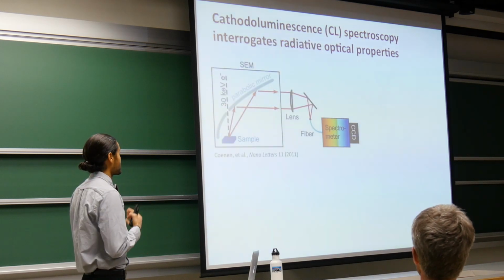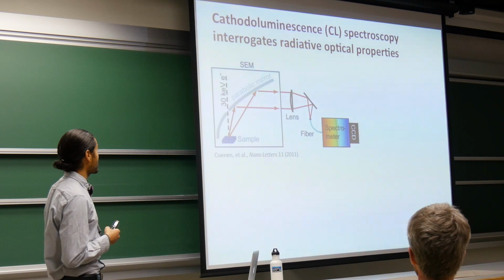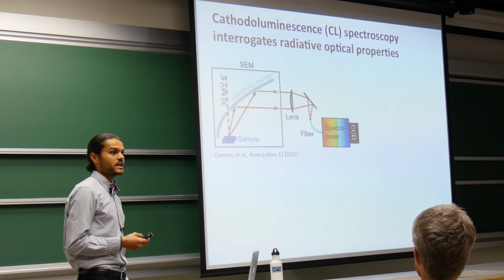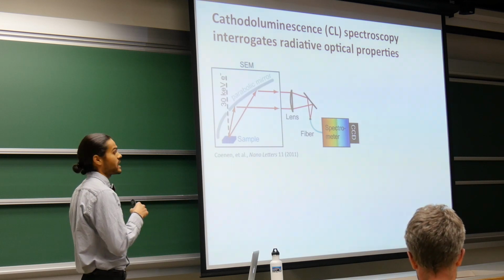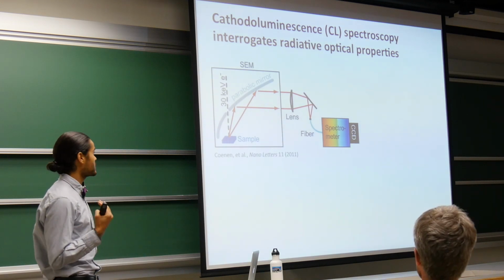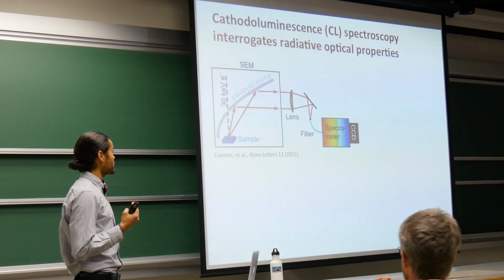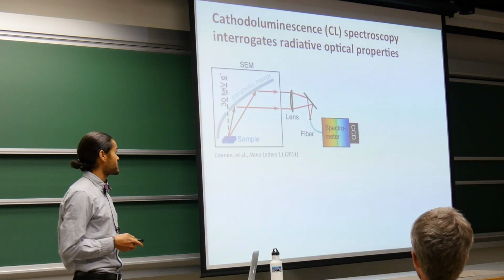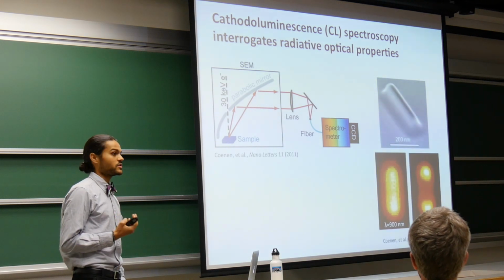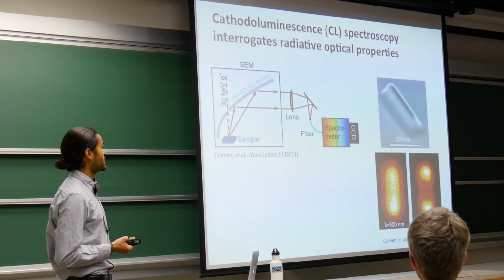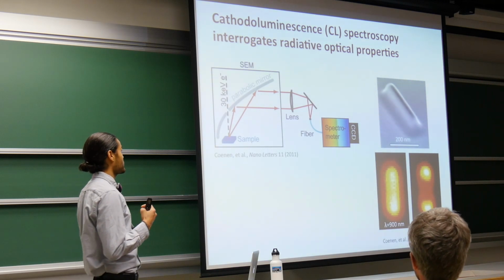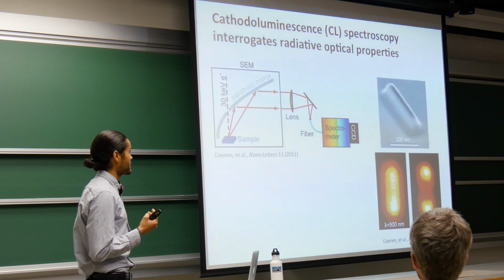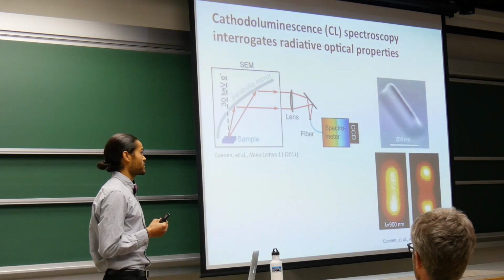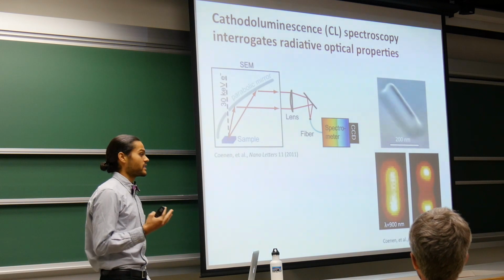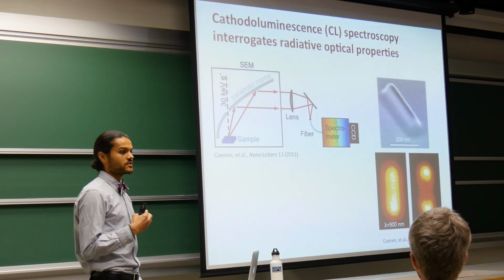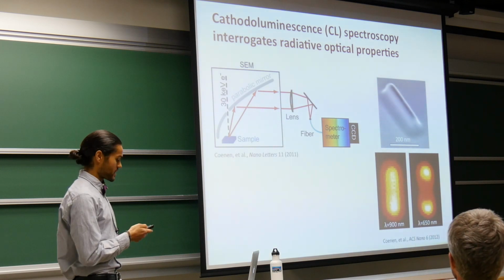Cathodoluminescence is essentially the emission of light upon excitation with an electron. So here we're looking at a schematic of a scanning electron microscope chamber where we have a paraboloid mirror that redirects this cathodoluminescence light emission outside of the chamber, and then it can be processed by a spectrometer and CCD. Here is a simple example to show you how this technique can be used to study nanoscale systems. This is a ridge antenna about 300 nanometers in length that has been created in a single crystalline gold sample. Now, depending on the wavelength of light that we're interested in, we can use this cathodoluminescence signal to map out the different modes of this structure.